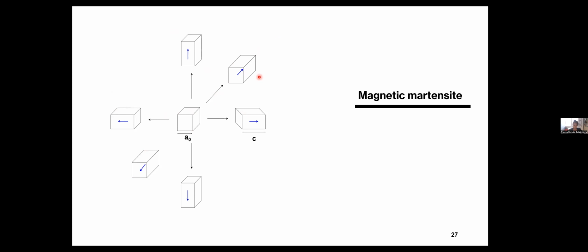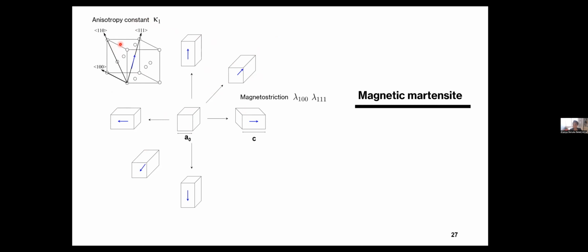And this paramagnetic to ferromagnetic phase transformation is not just accompanied by a structural distortion which satisfies different lattice geometries, but is also accompanied by new magnetic properties, the ones that we discussed. Now the material has an anisotropy constant. You have magnetostriction constants, which are associated with the change in length when you go from the paramagnetic to a ferromagnetic phase. And we expect that these material constants are going to play an important role when you want to have a stress-free interface. So the line of work that we're doing at the moment is trying to understand the balance between these different material constants for which we can stabilize a stress-free interface that's not just stress-free, but also satisfies the magnetization compatibility of being divergence-free.